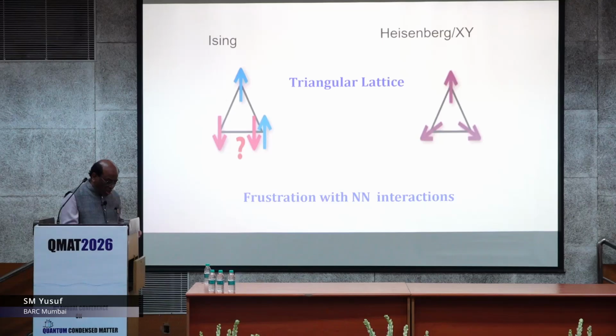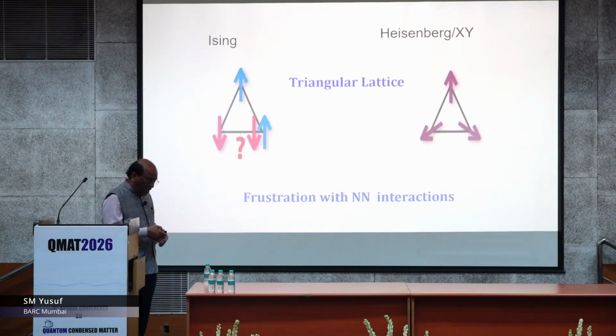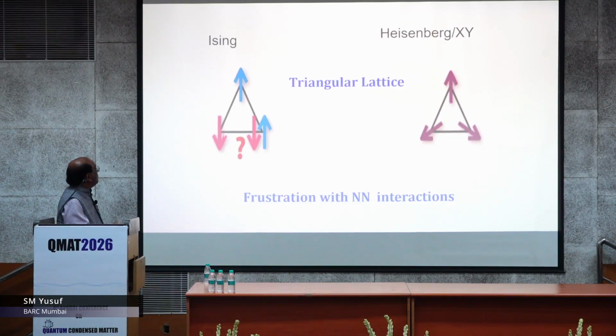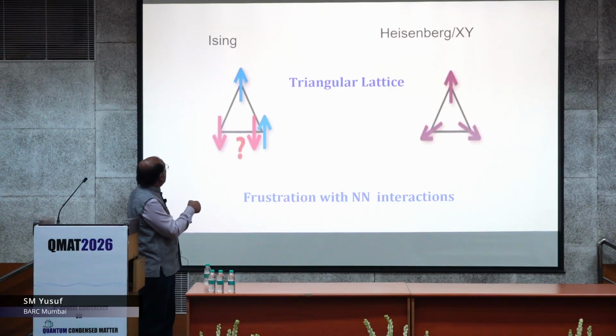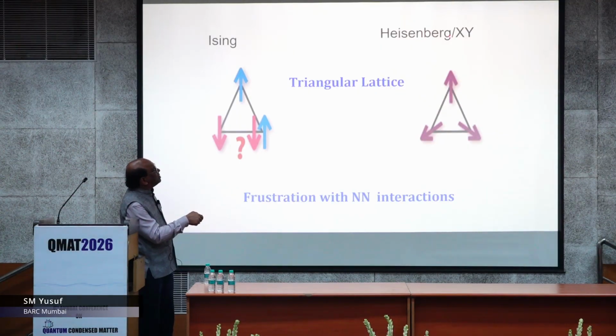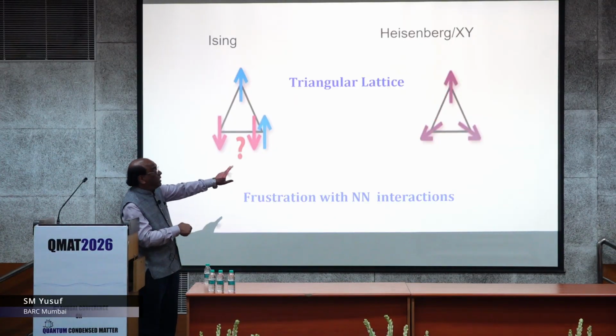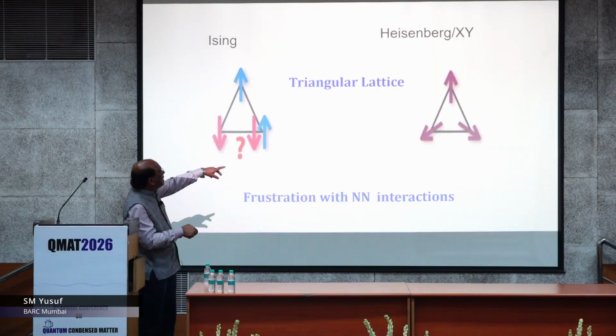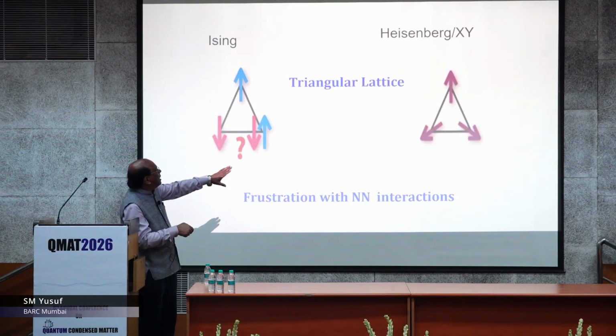Now when we talk about the frustration, as I said, the lattice geometry comes into the picture. Suppose you have this kind of arrangement, where the spins, moments are sitting at the three vertices and they are Ising type, that means they are restricted to align only in one particular direction, and there is a negative exchange interaction, so they have to be antiparallel. And once this is antiparallel and this is also a negative exchange interaction, this spin demands that this should be up, whereas this spin demands that this should be down, so this third one is frustrated. Of course, which third one, you never know. That is the Ising restriction. But if you deal with Heisenberg or XY spins, because they can orient in space, here that is not allowed, but there it is allowed. So this kind of arrangement takes place in a triangular lattice.